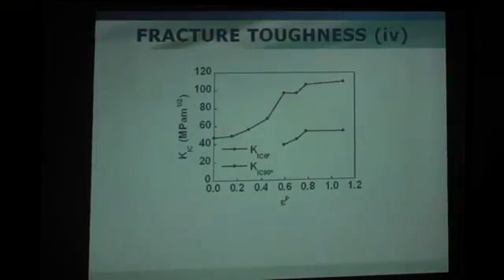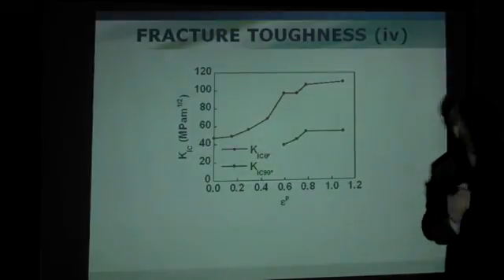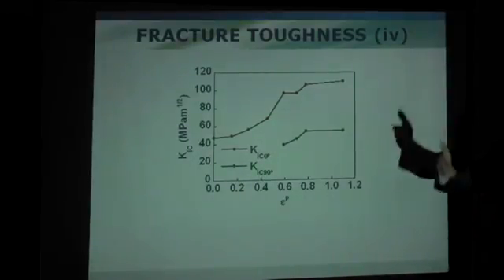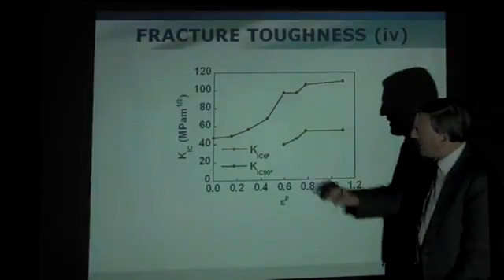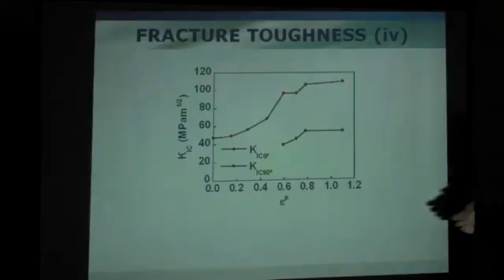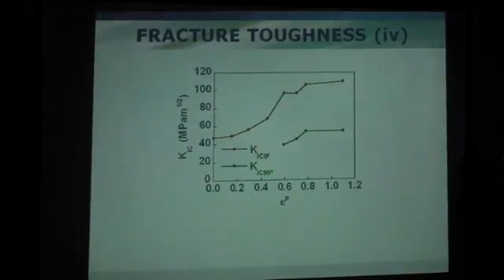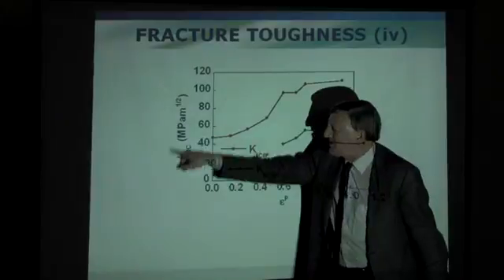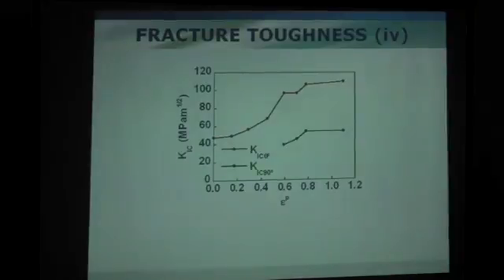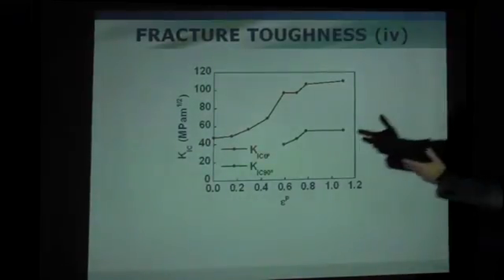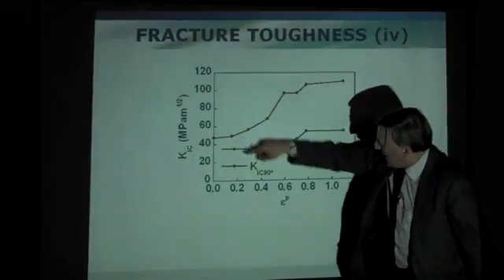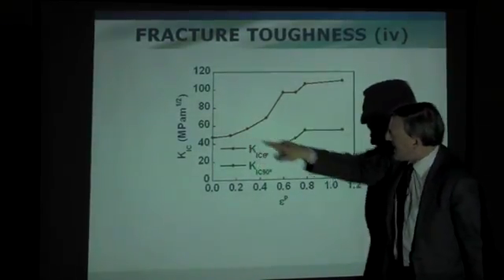With this consideration, we have two papers, Toribio and Pariente. One of them, the longer in Engineering Failure Analysis, explaining this procedure on the basis of the Amestoy and co-worker equation. And with this, we will finally obtain the K1C, or critical stress intensity factor, because the concept of toughness with mixed mode propagation could be dubious. Really it is a dimension with dimensions of K, but this is an energy release rate, directional. And we obtain this pseudo toughness in 0 degree and 90 degrees and for any degree.